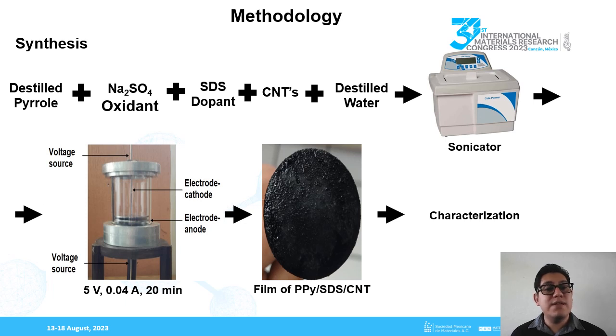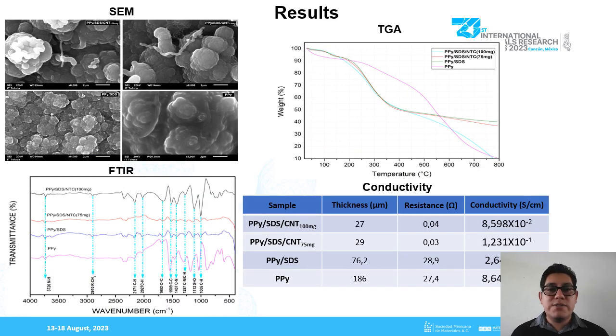We obtained different films: polypyrrole with SDS and with 75 milligrams of carbon nanotubes, polypyrrole with SDS, and polypyrrole only. Their morphological, structural, thermal, and electrical properties were characterized using scanning electron microscopy, Fourier transform infrared spectroscopy, thermogravimetric analysis, and the two-probe method, respectively. As for the results, the polypyrrole is observed with the characteristic cauliflower shape, while in those containing carbon nanotubes, the polypyrrole grows on them, and protruding elongated forms are observed.